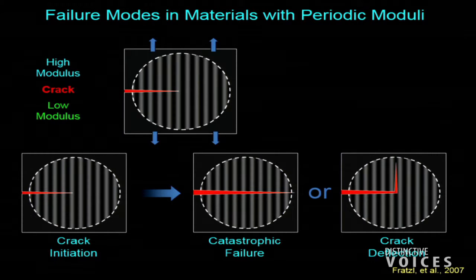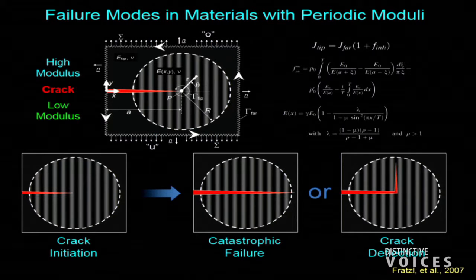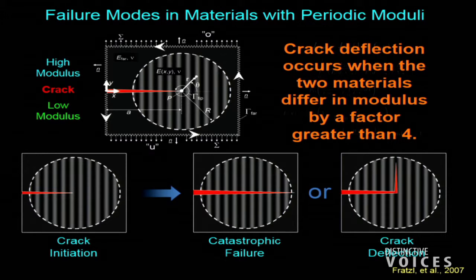If you take a ceramic plate, your dinner plate, you drop it on the floor, what happens? It fractures catastrophically. But composite materials where you have a high and low modulus, and this is what the quiz will be about right here, basically it boils down to, if the difference of the stiffness is greater than a factor of 4, we would expect to get cracks deflecting at interfaces. So what biology does is they'll assemble materials in a hierarchical structure with these interfaces so that a crack propagating will not go right through, it will have to be deflected. And there's a lot of energy absorption or toughening that occurs due to this.